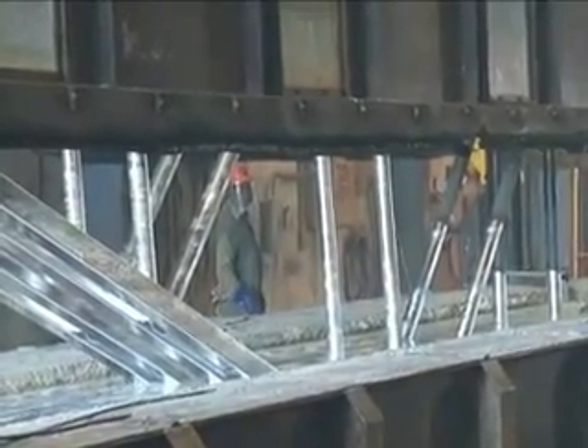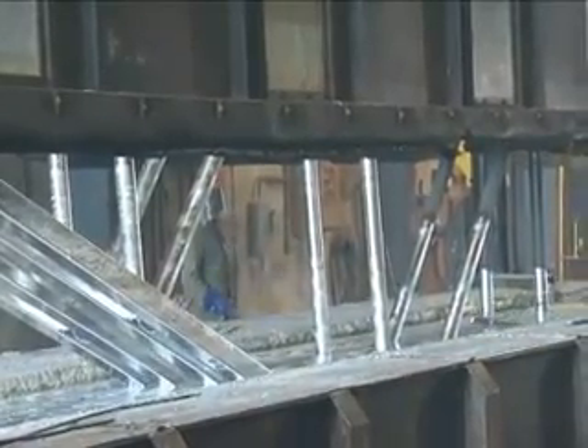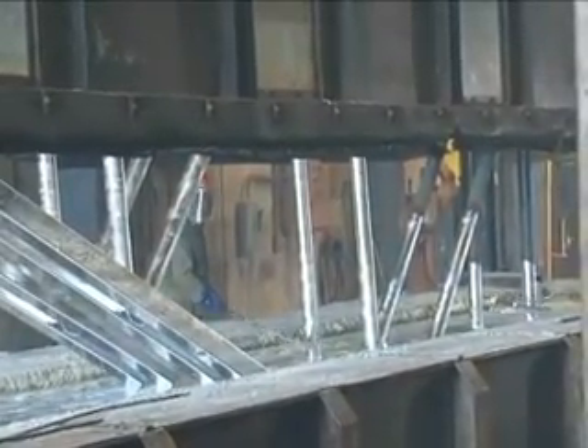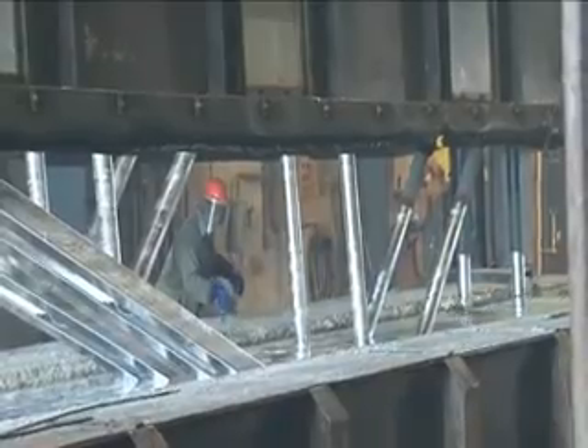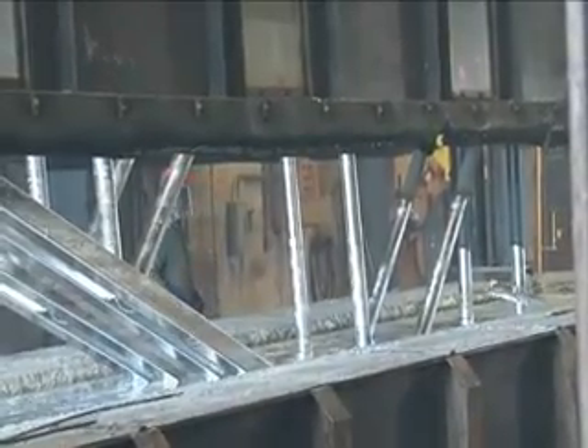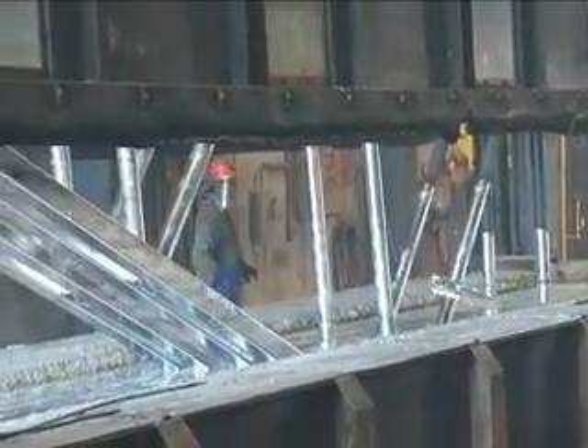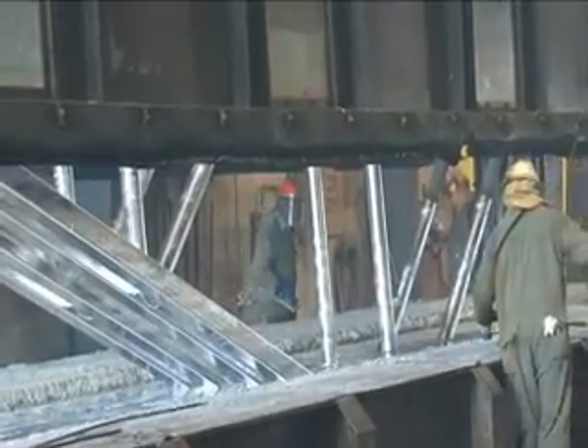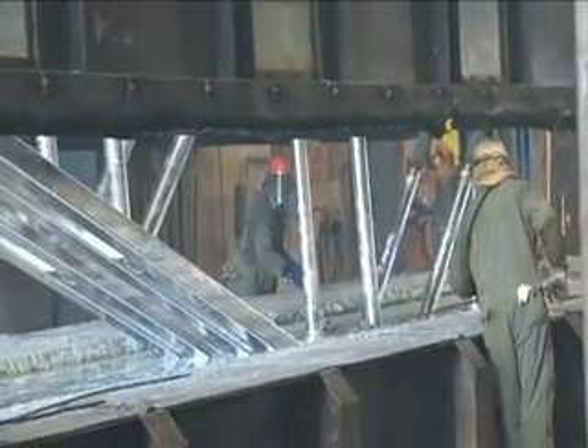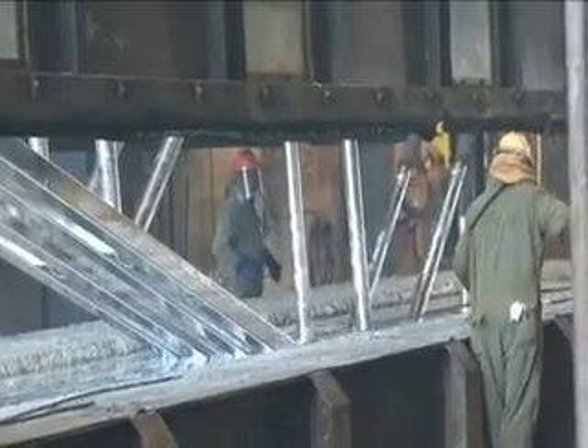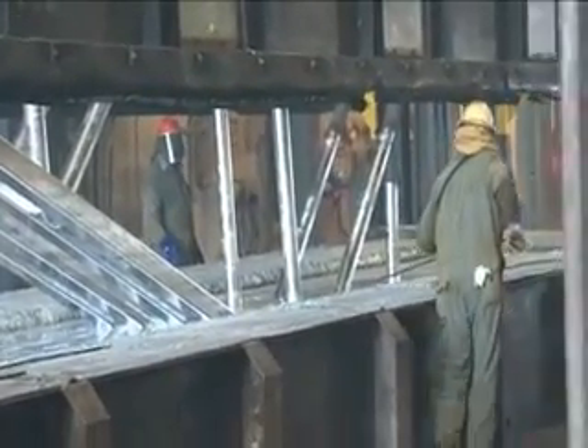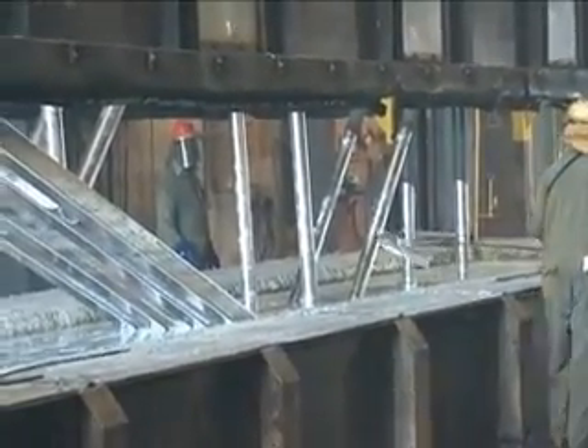Zinc is a metallurgical bond to the steel. That's why the kettle is at 845 degrees. The product has to sit in the kettle long enough to get up to that kettle temperature. When that happens, then you have the metallurgical bond between the zinc and the base steel. And because of that, you could scratch the zinc, and if you happen to go all the way through the zinc into the bare metal out in the field, it's not going to rust.